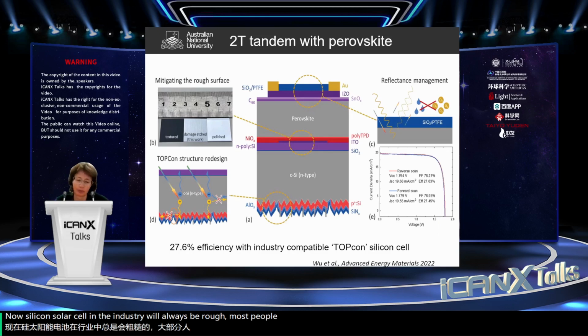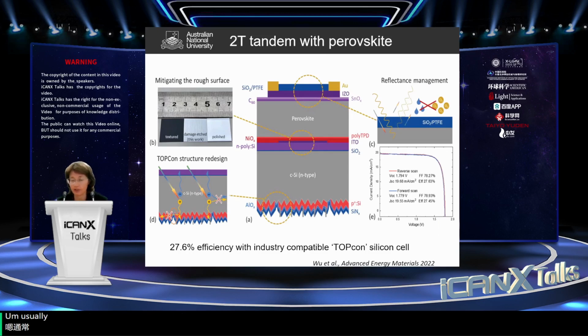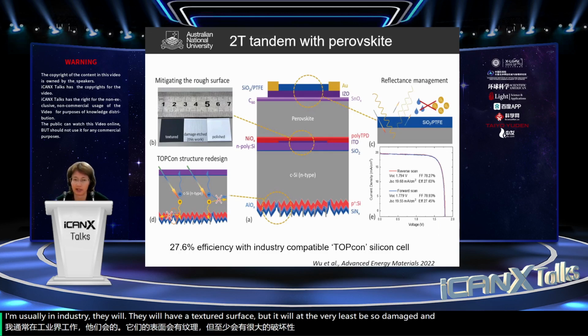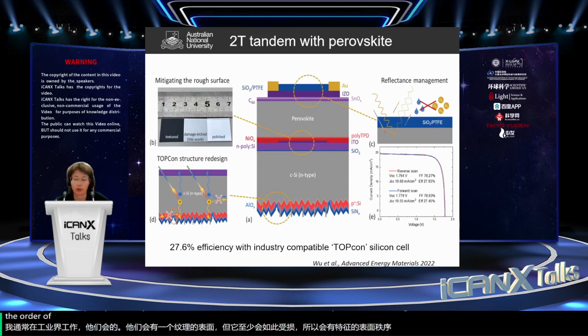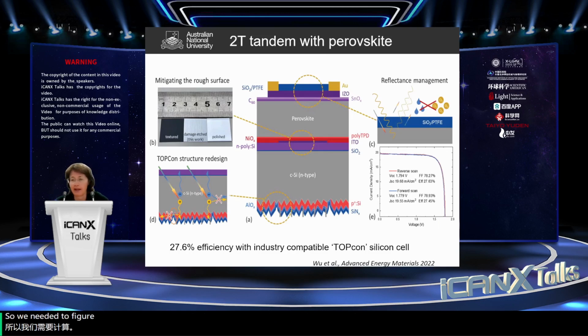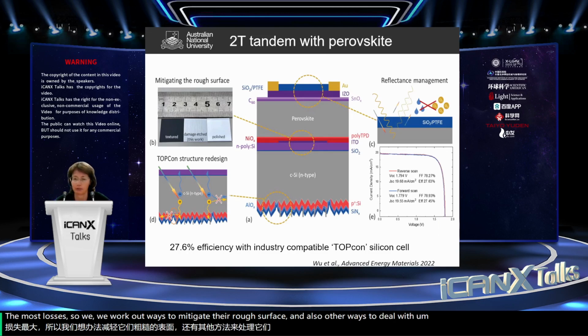Most people, when they're making cells in the lab, will use a polished silicon wafer. But that's just completely impossible in industry. It's very expensive to polish silicon. So usually in industry, they will have a textured surface, but it will at the very least be saw damaged. And so there will be features on the surface of the order of a micron or so. So we needed to figure out how we could manage those losses. So we worked out ways to mitigate that rough surface and also other ways to deal with reflection.